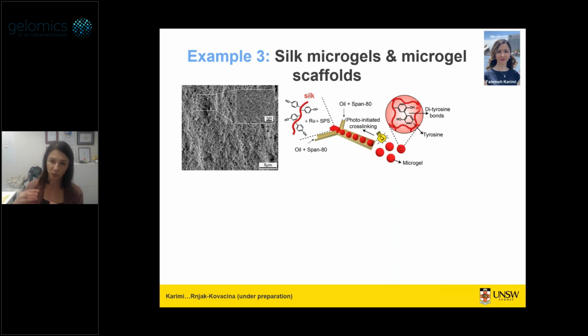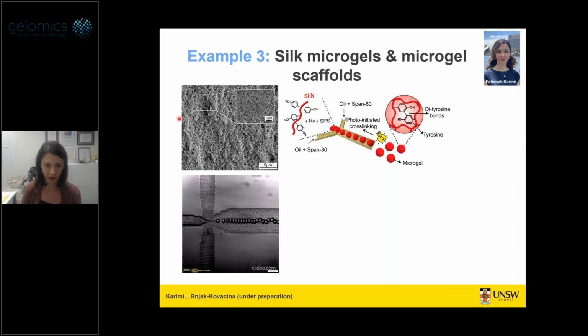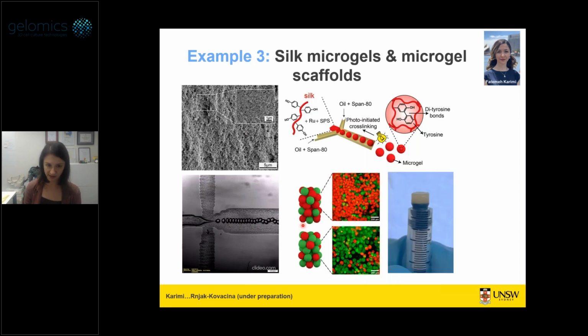And because this reaction with ruthenium is so quick, we are actually able to capture these little microgel spheres as they're coming off this microfluidic device here. But the cool thing about these is that you can now start packing them together, and because they're rounded, they're not going to pack perfectly. And so between them, you're actually going to start getting porosity. And so now you have all the properties of the hydrogels with the micron scale porosity between them. And you can make them into these scaffolds like here.